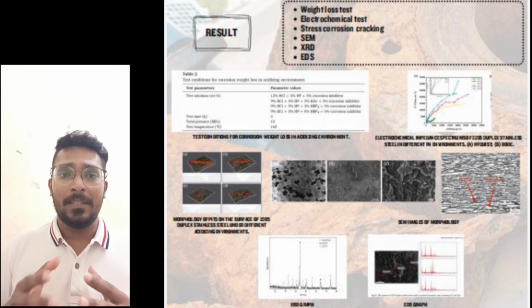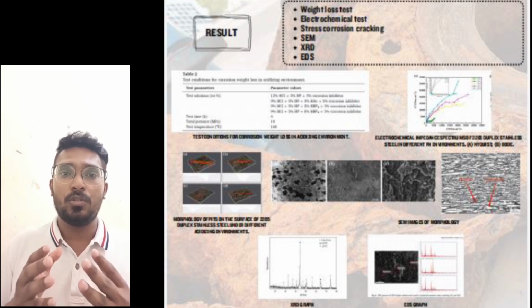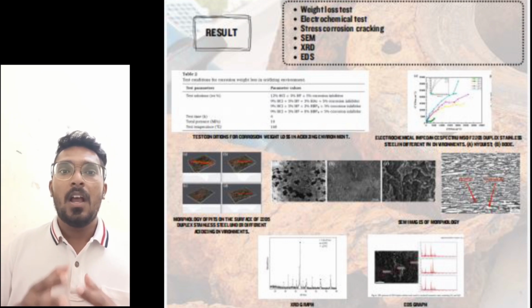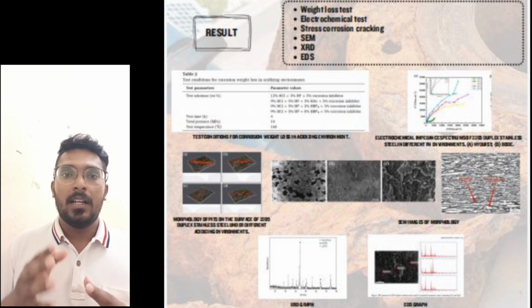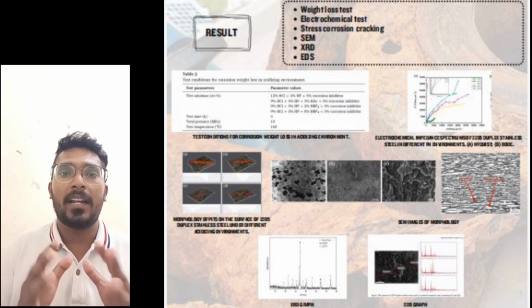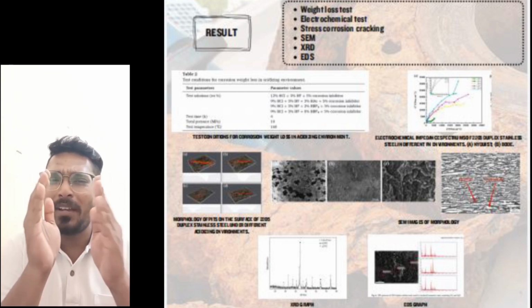Okay, continuing with the SEM test. SEM images show the corrosion pits on 2205 duplex stainless steel samples in the simulated formation water with hydrogen sulfide and carbon dioxide, but no cracking. High magnification SEM confirmed that there is no cracking at the bottom.